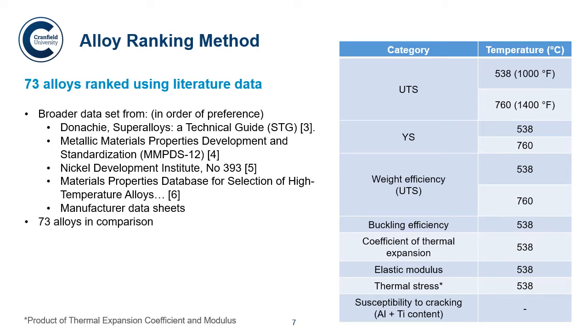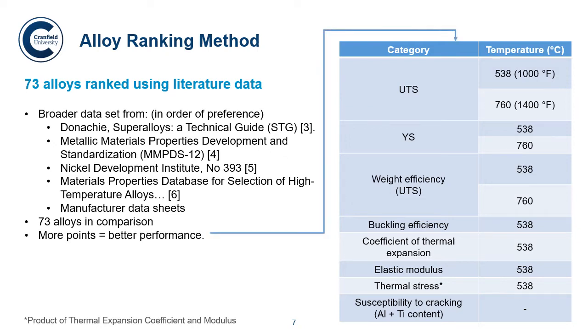So we have 73 alloys in comparison in total. More points equals better performance. As you can see in the table on the right, we have lots of different categories and temperatures at which we're going to be ranking the alloys. To start with, we have ultimate tensile strength, tested at two different temperatures. The first is 1000 Fahrenheit and 1400 Fahrenheit. All of these temperatures are actually converted from Fahrenheit.